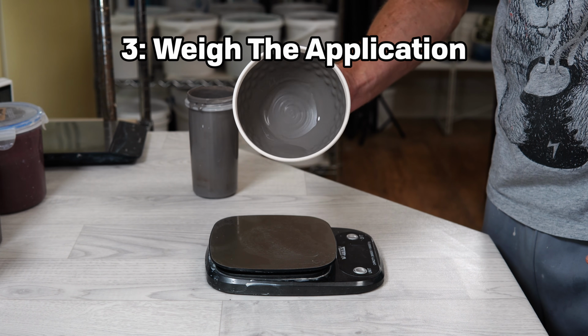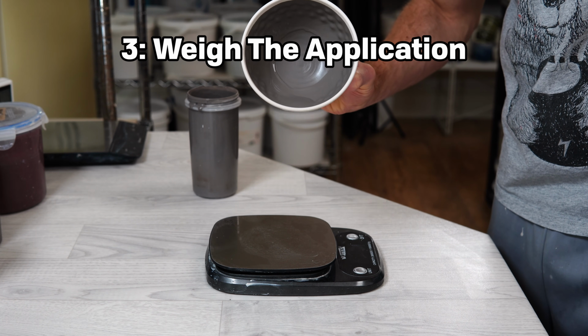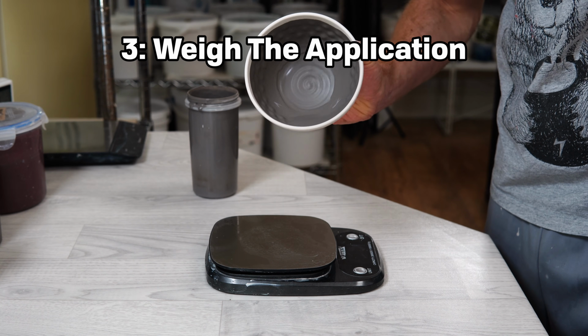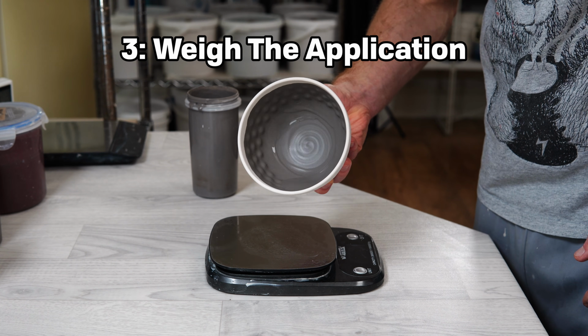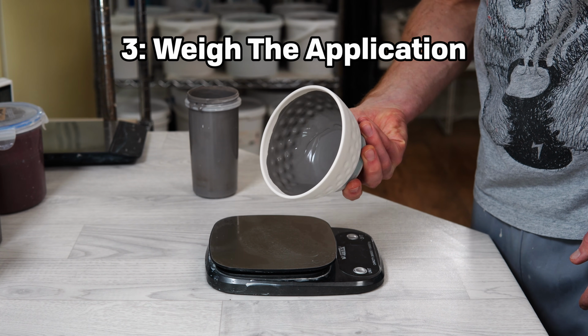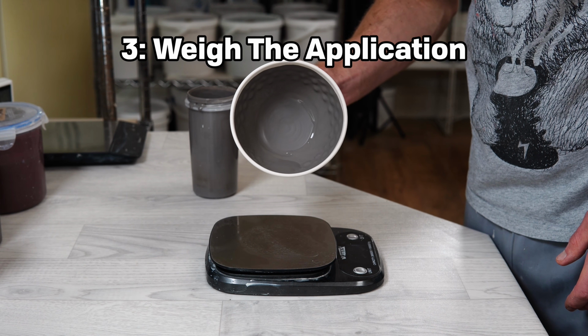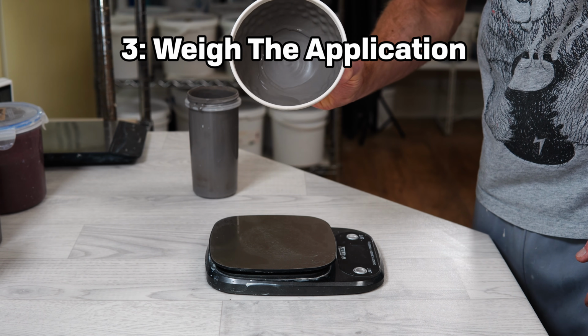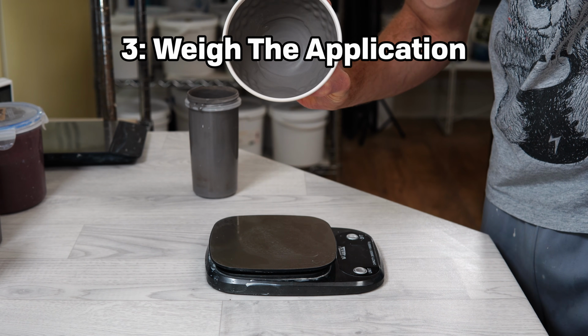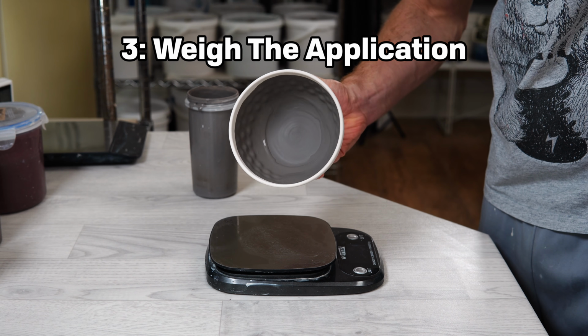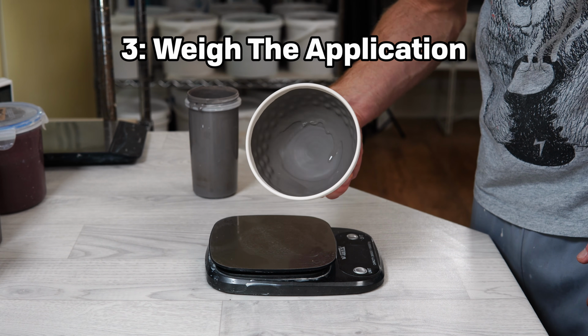Alternatively, if you weigh the piece before glazing and then allow the glaze to fully dry and weigh the piece afterwards, you will have the dry weight of the glaze, which can also be useful. Once you've established your target number for weight of glaze per piece, you don't need to weigh every single piece, but knowing what the right application weighs will be invaluable if you start having issues with consistency.